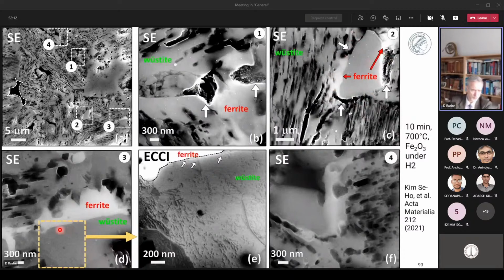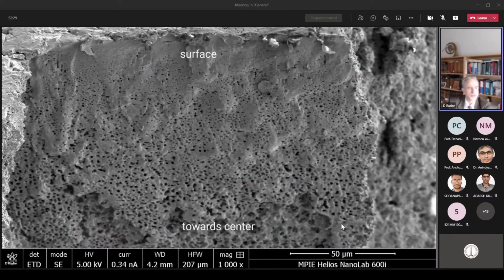You also see here, when you get closer to some of these interfaces, that you build up, as you can see in the channeling contrast, very high populations, for instance, of dislocations. And so there's an interplay of that porosity, as you see here, and the stresses. The porosity comes from the oxygen loss. So we show that here on this slide for a wüstite single crystal. Close to the surface, the porosity gets very fine and the oxygen in part can directly diffuse out of the surface when the reaction starts.